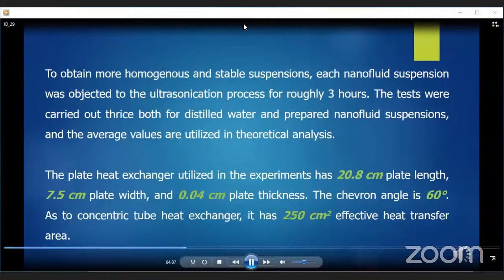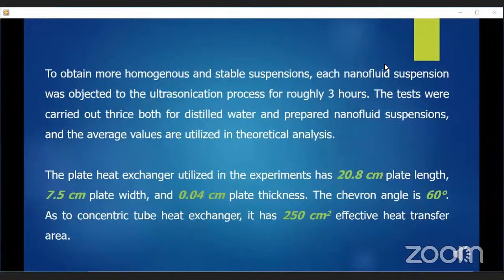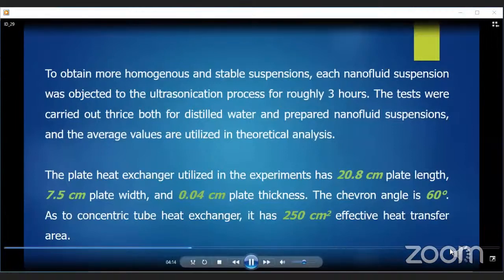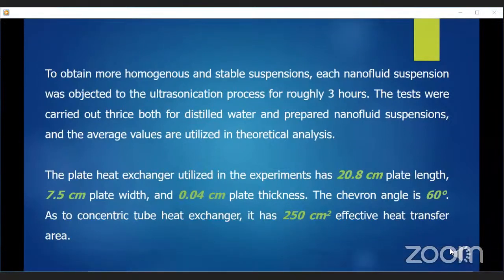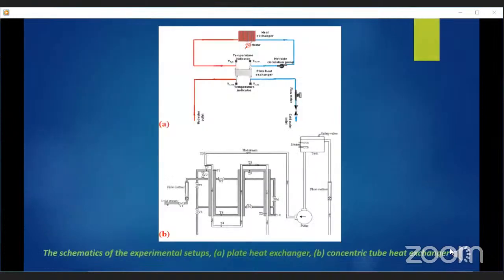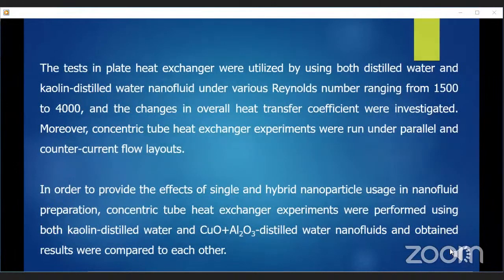The plate heat exchanger utilized in the experiment has 20.8 cm plate length, 7.5 cm plate width, and 0.04 cm plate thickness. The chevron angle is 60 degrees. As to the concentric tube heat exchanger, it has 250 cm² effective heat transfer area. The schematics of the plate heat exchanger and concentric tube heat exchanger can be seen in these figures, respectively.